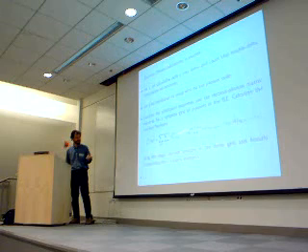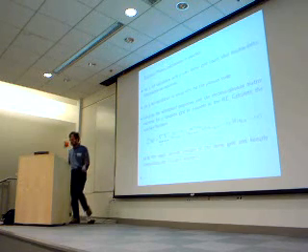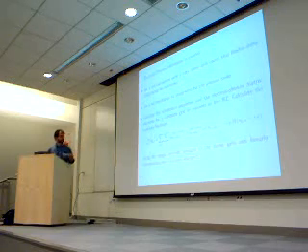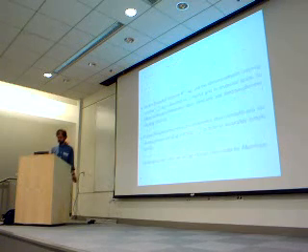So once you have done this integral accurately by linearly interpolating these two objects, then the integration over the Q space, over the reciprocal space with respect to the phonon momentum, can be done very efficiently, because there you can use the Fourier interpolation.